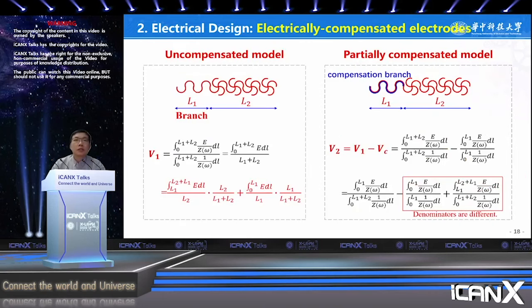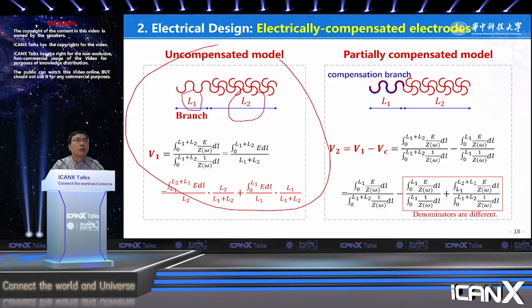The electrode in the left frame is a general one without the compensation part. The length of the electrode is L1 plus L2. So this is the total electrode. One can get the electrode potential V1 based on the distributed parameter model. It can be noted that the final potential contains the effect of part 1, contains the part 1 potential. So like this one.